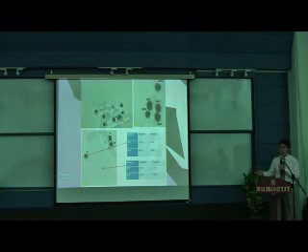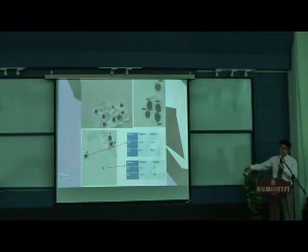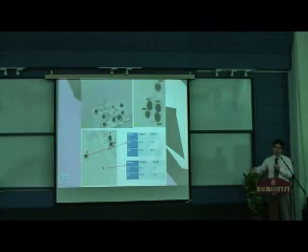And of course, almost controlled size and shape. No triangle, no hexagonal, and other forms that we saw in the previous case. So we believe this is a seed-controlled synthesis of gold nanoparticles with the help of in situ generation of palladium nanoparticles, with the help of leaf extract.